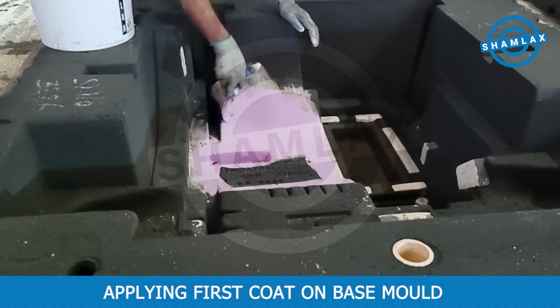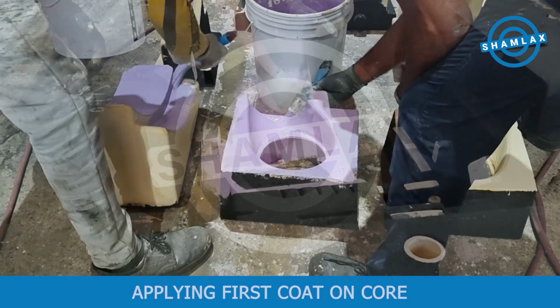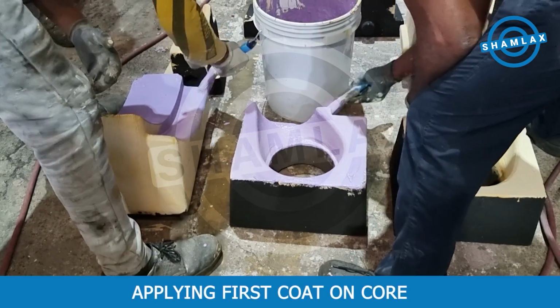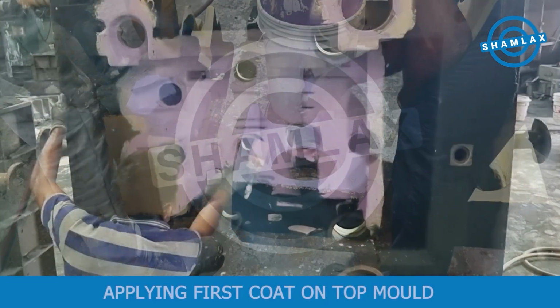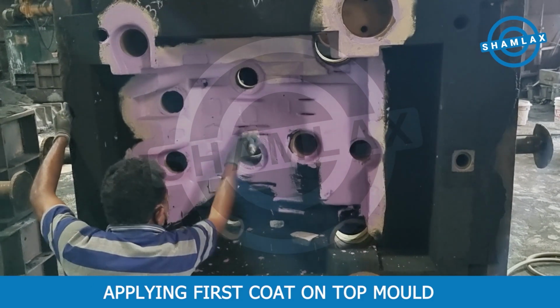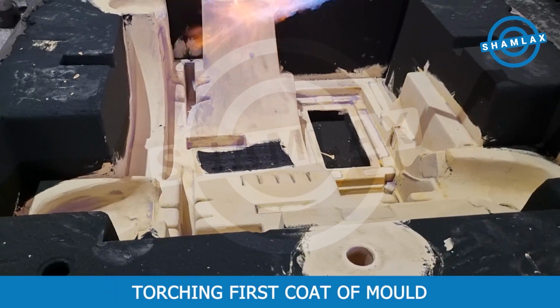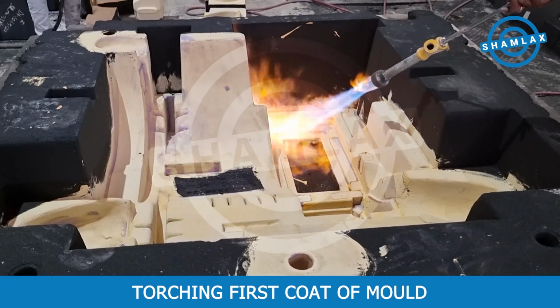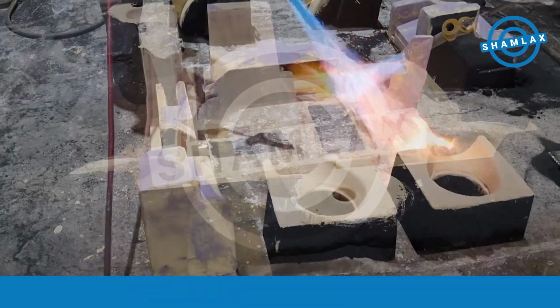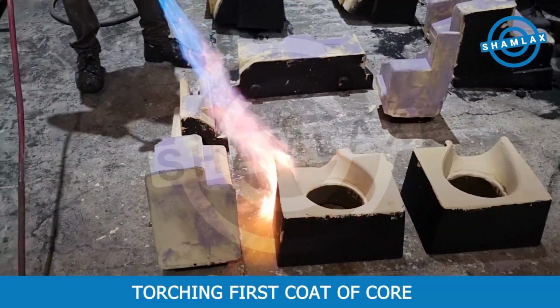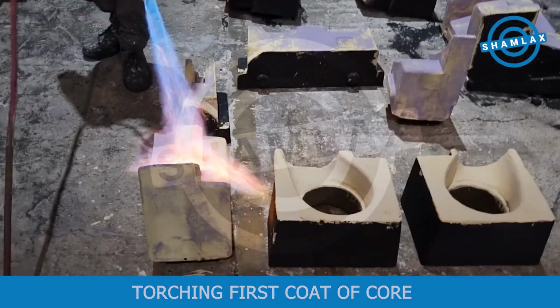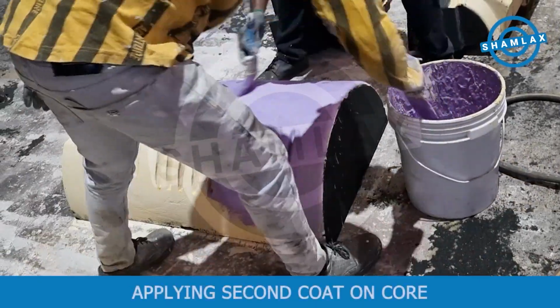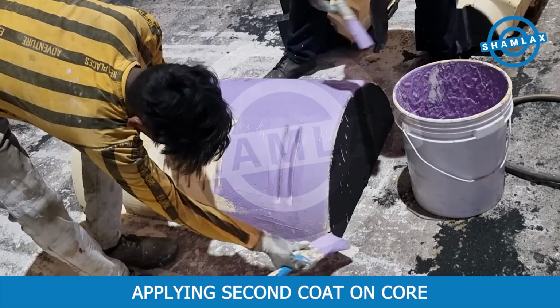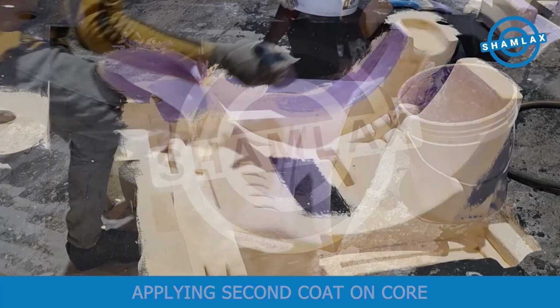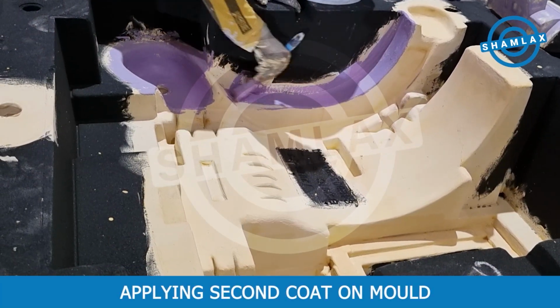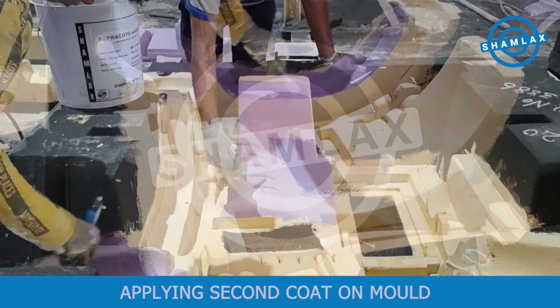The final application is for carbon steel grade. The weight of the casting is around 950 kg. With this coating, we, at Shamlax, have provided a single-step solution for eliminating all casting-related defects.